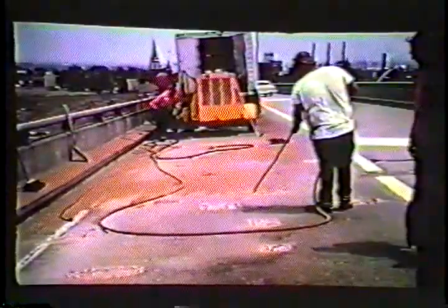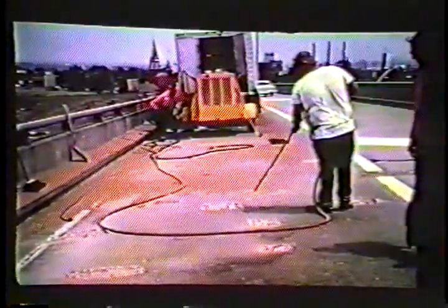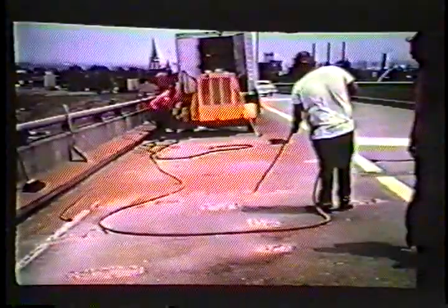First, we need a hole that is reasonably square. Epoxy patches, if done right, don't require sawed holes. But doing it right requires clean, dry holes. This means sandblasting the hole. If you don't, you may have surfaces such as this where mud and moisture will prevent good bonding. Then the area must be cleaned with an air nozzle. This is to eliminate the dust, sand, and moisture in order to develop good bond.